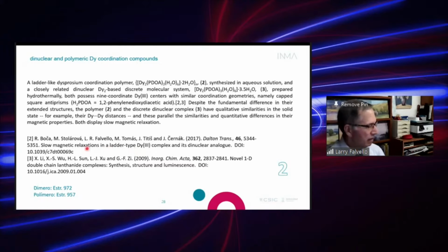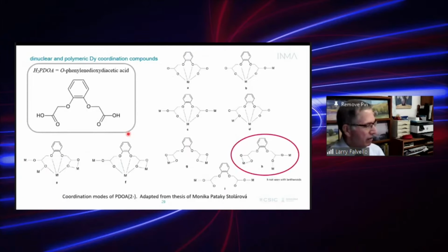This was all written up way back when, in 2017, and both of these compounds have slow magnetic relaxation, but I won't talk about that aspect of it. Well, PDOA is a great ligand. It accommodates metal atoms in a host of different ways. There are at least 9 ways known, and all of them except the one enclosed in the red ellipse here, all of the others have been observed for lanthanoids. And in our two complexes with dysprosium, we actually observed 4 different coordination modes of PDOA.